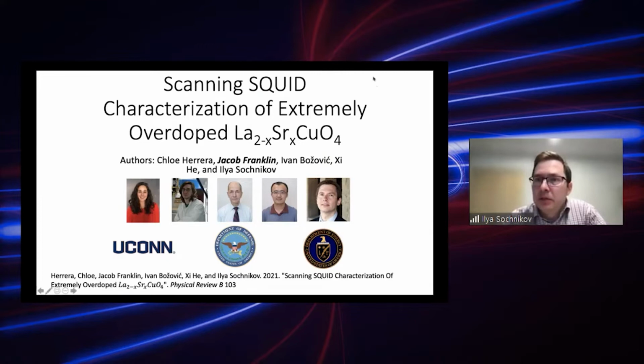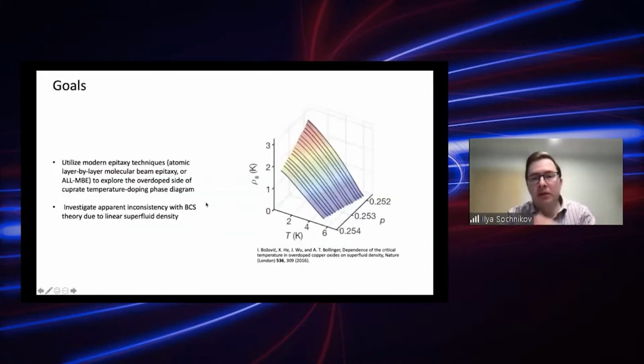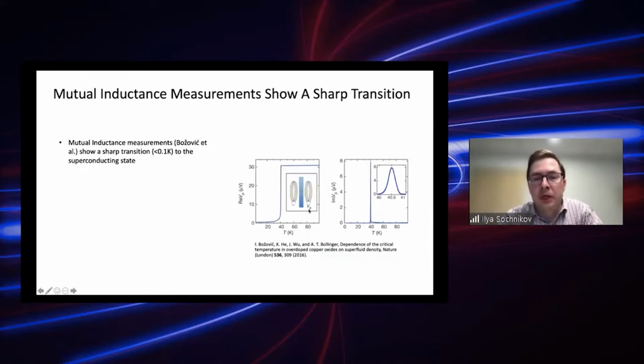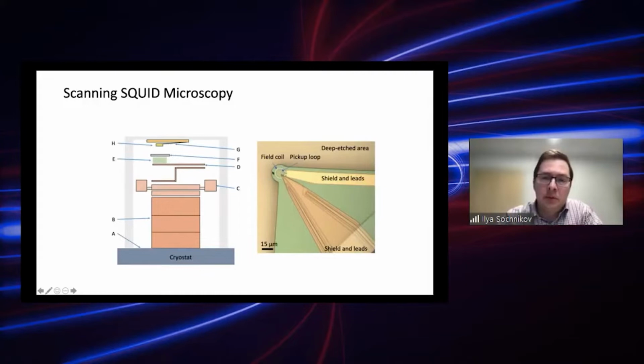So this part is on the overdoped samples. Like I said, this is published in the PRB. The motivation for this work comes from the 2016 Nature paper by Ivan, where they showed that the superfluid density, or superfluid stiffness, on the overdoped side, quite surprisingly, follows pretty much a linear dependence. This is not described by the BCS theory, and in general is hard to describe theoretically. So some of these questions were: what if you have a film that is non-uniform, and this superfluid stiffness on a millimeter scale, which is what Ivan measures with a mutual inductance technique? What if you have some non-uniformity that averages out to this kind of linear dependence? This is what we were after to probe with the scanning SQUID technique, which is essentially a mutual inductance technique, but on a micron scale.